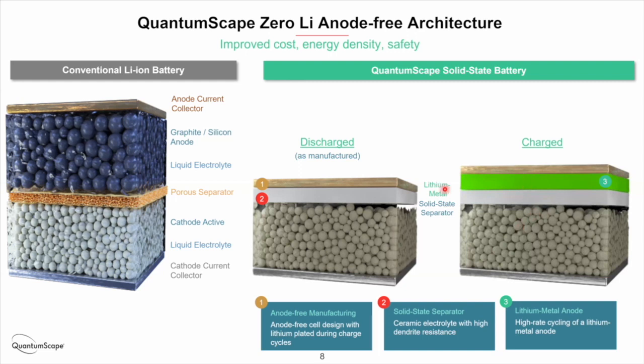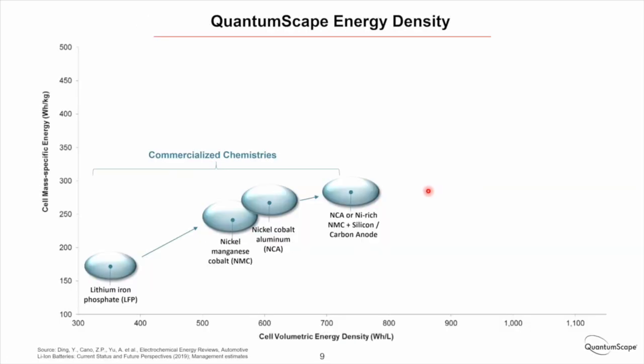So one of the keys here to enabling this architecture is the separator. So we replaced the porous polymer separator with a dense ceramic separator here that sits between the anode and cathode. And it's this separator that's a key, I think, to enabling lithium metal, as we'll talk about. So what does this change enable in terms of energy density? So this is a map then of mass-specific energy density, or watt hours per kilogram, on the y-axis, and volumetric energy density on the x-axis, showing the range of commercialized chemistries from lithium iron phosphate or LFP chemistries, which are low energy density but low cost, to what's more common in electric vehicles, at least the ones outside of China, using an NMC or, as Tesla uses, NCA cathodes.